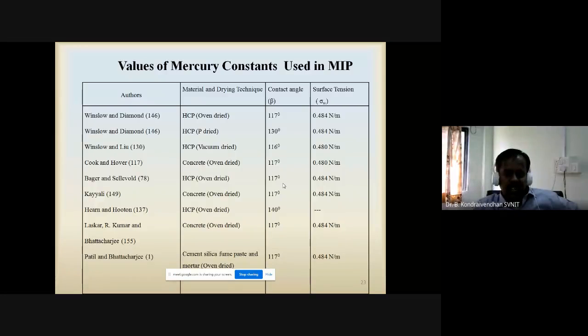Okay. Then, as I mentioned, mercury intrusion porosimetry follows the Washburn equation, and again the Washburn equation is a function of contact angle and surface tension. So one has to determine the contact angle and surface tension before operating this instrument. For that also, a number of people have done a lot of research on this, so different drying techniques are also used. Based on the drying technique only, we have to choose the contact angle and surface tension.